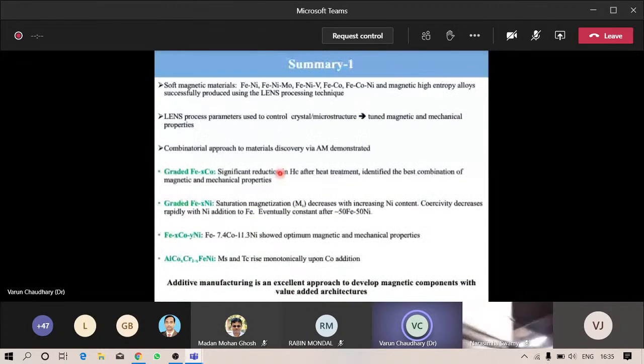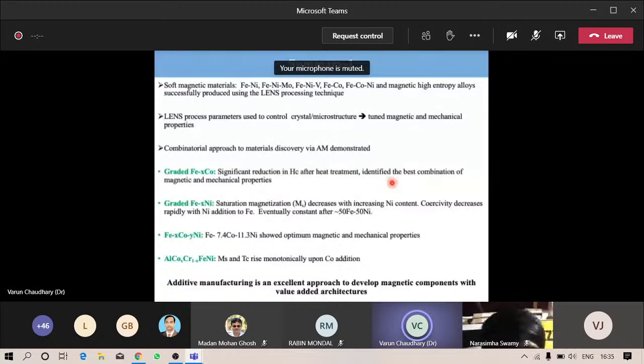Here I summarize the first part of my talk. We have developed iron-nickel-vanadium, iron-cobalt-nickel, and magnetic high entropy alloys using the LENS processing technique. LENS process parameters were used to control the crystal structure and magnetic properties. The combinatorial approach to materials development via additive manufacturing has been demonstrated. For the graded iron-cobalt, a significant reduction in coercivity after heat treatment was observed, and we identified the best combination of magnetic and mechanical properties.